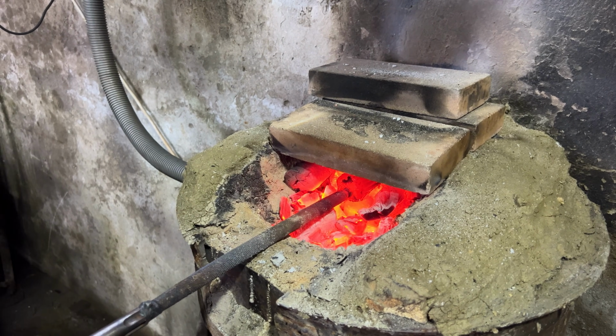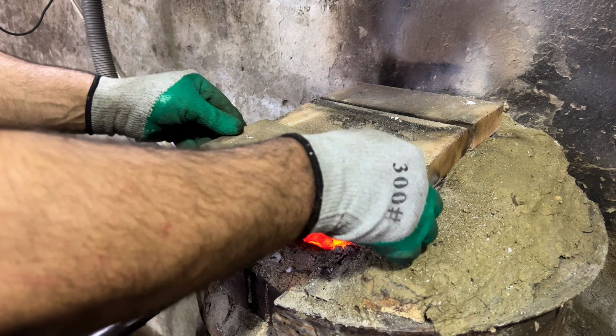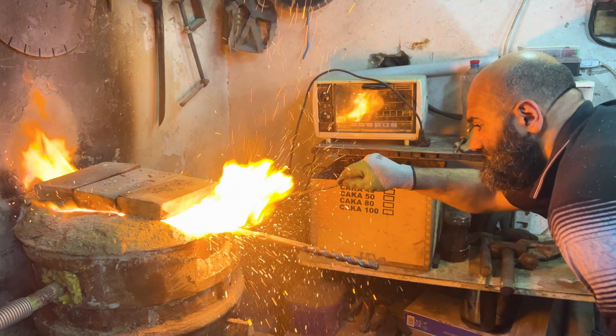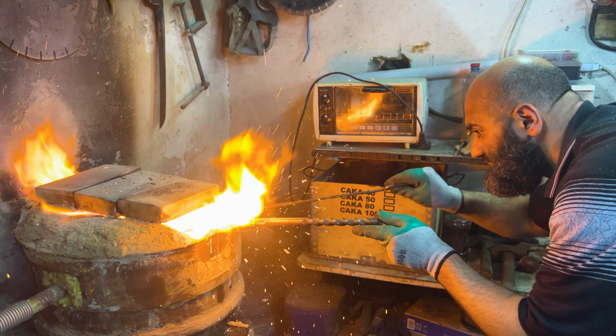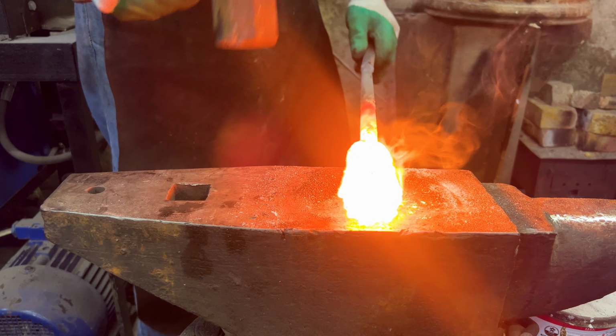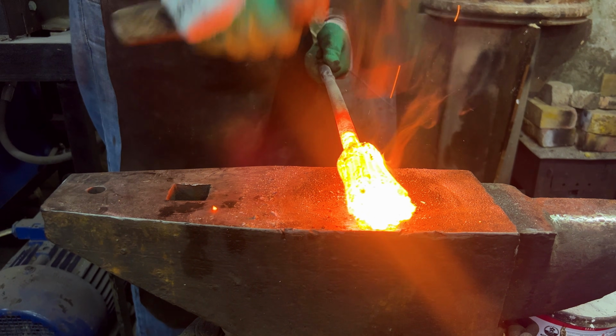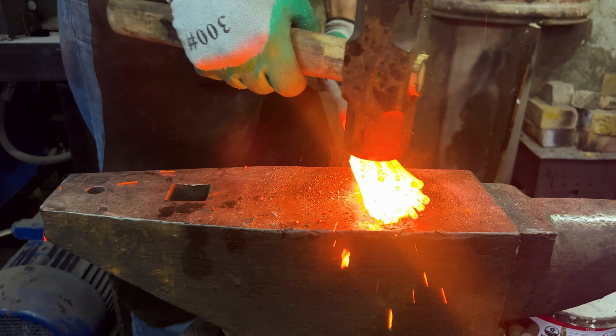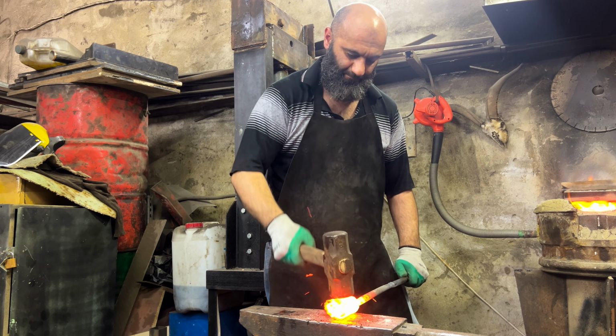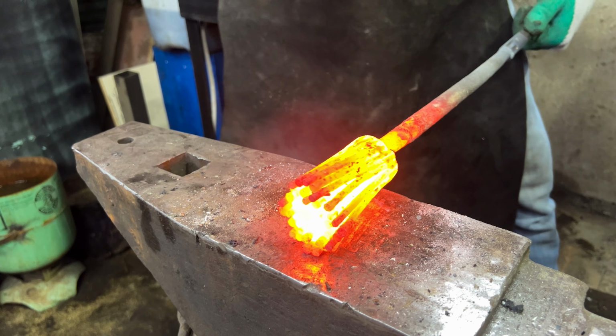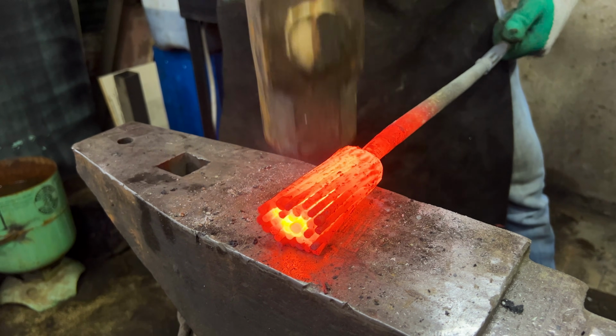Back into the fire. We are aiming for a solid welding heat here, roughly 1200 to 1300 degrees Celsius. You know it's ready when it glows like the surface of the sun and starts spitting at you. I'm hammering it gently at first to set the welds without blowing the bundle apart. Notice how the borax creates that liquid glass coating? That's exactly what we want.